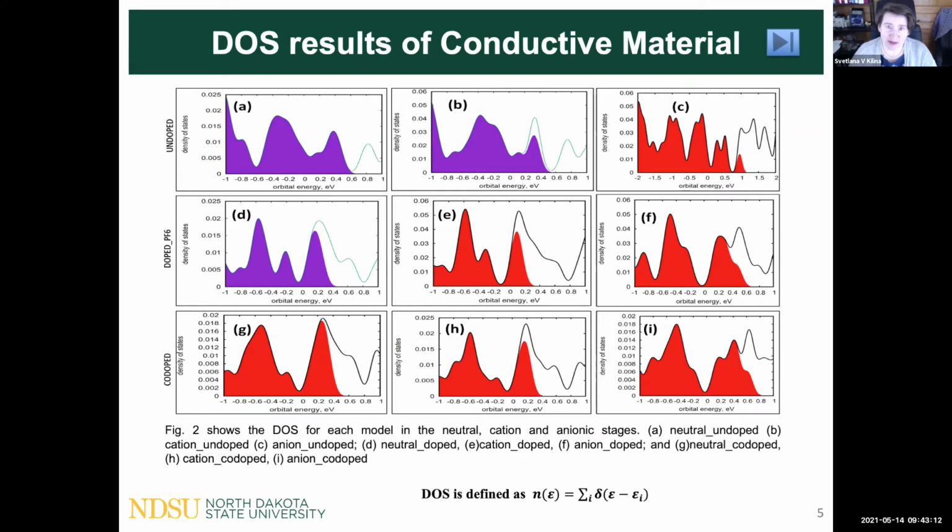So the gap really depends on the functional which you use, and GGA functionals are known to underestimate the band gap for semiconducting materials. So usually they do not agree with experiment. It would be really surprising if they did. It is a common failure of GGA functionals such as PBE that they make the gap smaller compared to the actual one. And there is a reason, but I will stop the discussion here. This reason will probably be another question to another student.